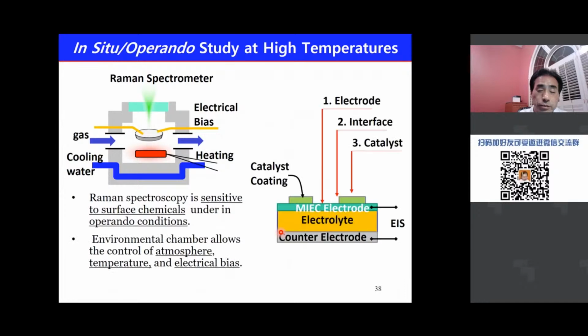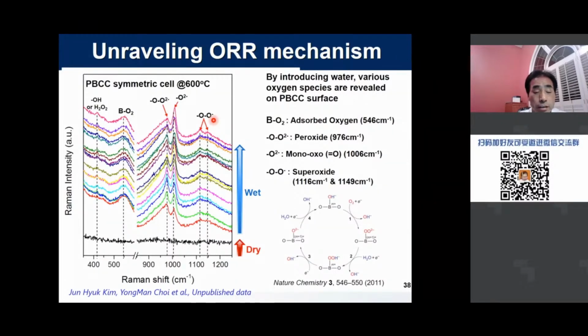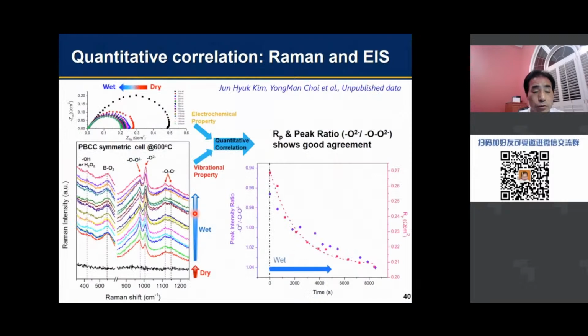And we're using in situ Raman measurement here to try to probe what the species on the surface are, as we collect electrochemical measurements. For instance, this is the Raman spectrum when the air is dry, and once the water is introduced, you see the evolution of the Raman spectrum. Now we're able to observe a lot of the oxygen species as a function of time and different conditions. So you can not only collect spectral information about surface chemistry, but also the electrochemical performance of the electrode.